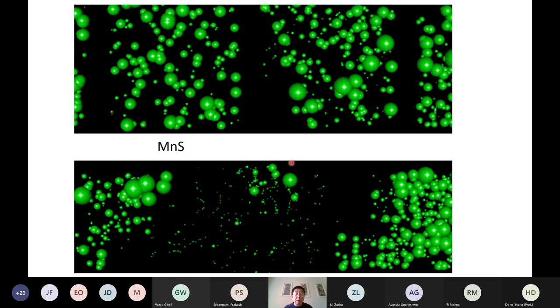However, we still have some inclusions here, but if you look at the pattern, those inclusions are distributed in a certain pattern, like a dendrite. So this manganese sulfide inclusion was formed during solidification of the steel. You can see they are at the interface.